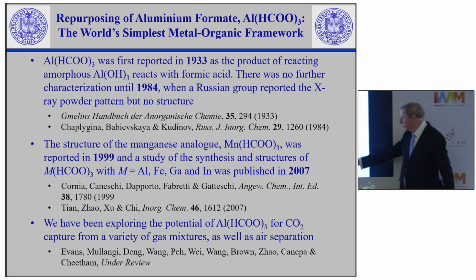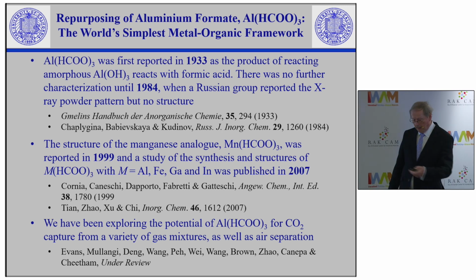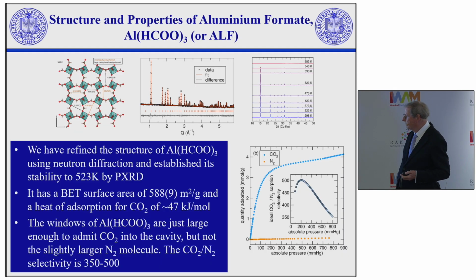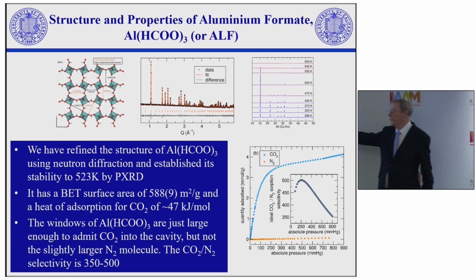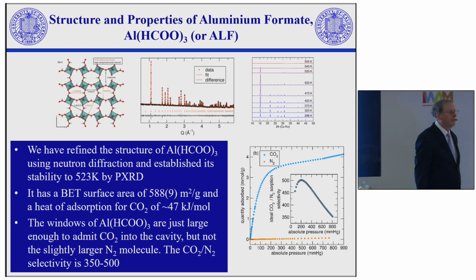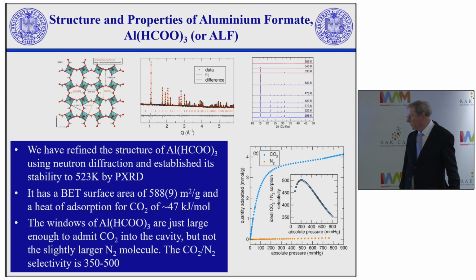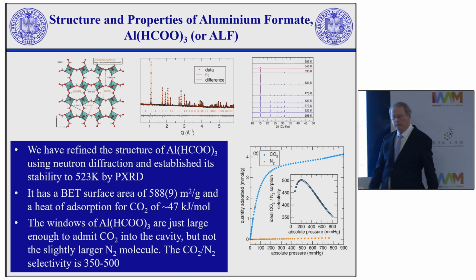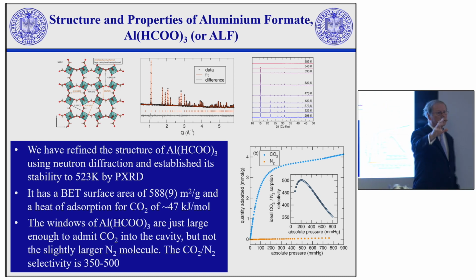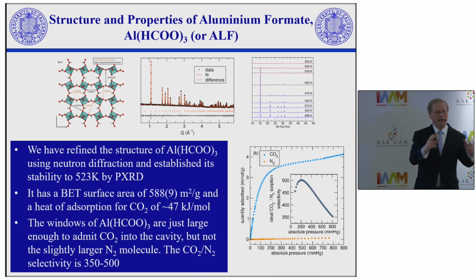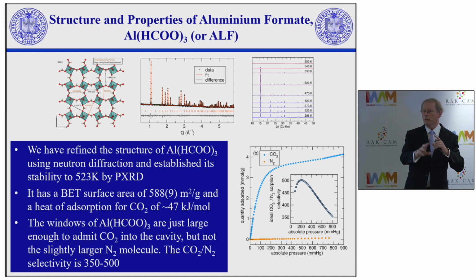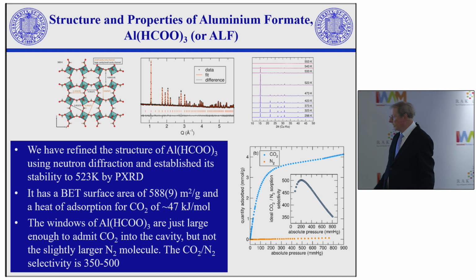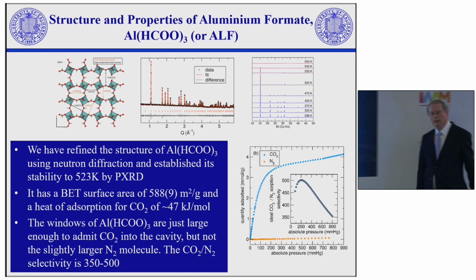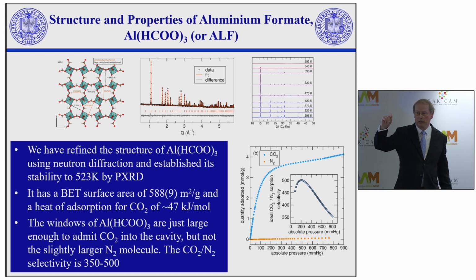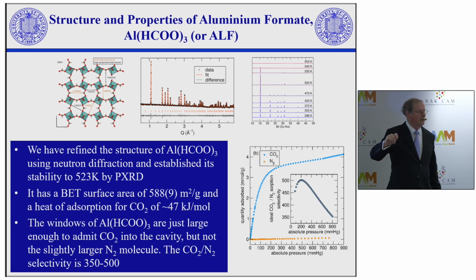And so we've been looking at this aluminum formate for CO2 capture. And this is a really interesting system. We call it ALF, aluminum formate. It's always nice to have a quick acronym. So ALF has some very special properties. It's a bit like the zeolites I talked about earlier. It's got cavities and channels and so on. But what's special about it is that the cavities are just large enough to let carbon dioxide go into it, but they're too small to let nitrogen, for example, go into it. And this is an incredibly small difference. The difference between CO2 and nitrogen is like the difference that Linus Pauling worried about. It's a billionth of a centimeter.